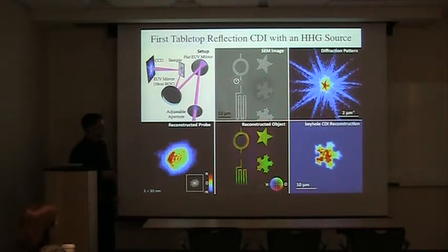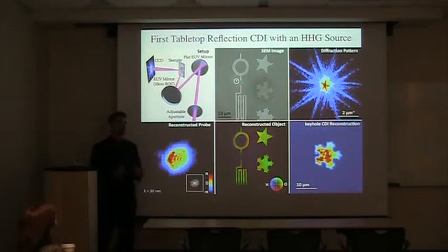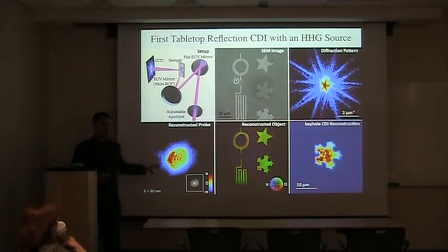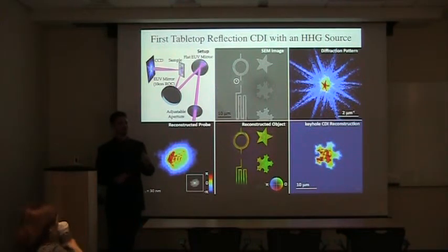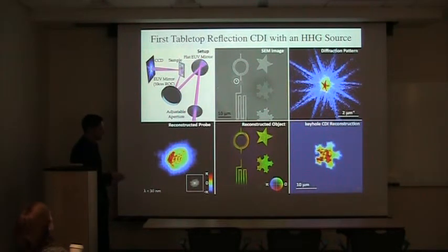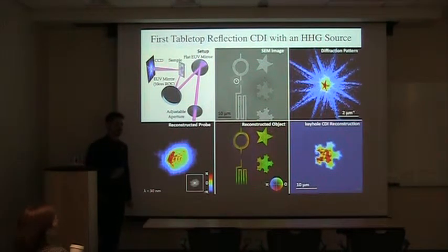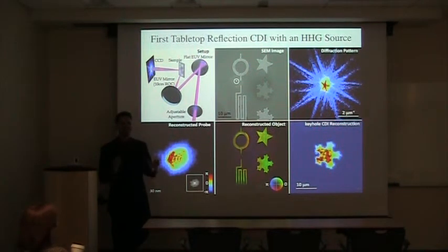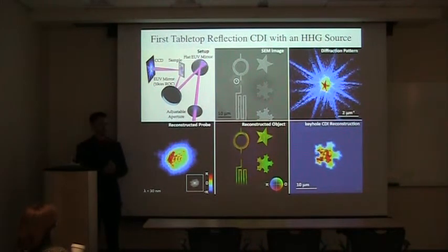Okay, like I said before, this new technique called ptychography is more or less a blind deconvolution algorithm. From it, you get your object and your beam, but it does require multiple diffraction patterns. Now, keyhole coherent diffractive imaging, if you know the beam, only requires one diffraction pattern, so it lends itself to dynamic studies. So you can get the beam from ptychography from this blind deconvolution algorithm using many diffraction patterns, and then plug that into the keyhole coherent diffractive imaging technique. So we have a lot of different techniques that we can use to do this imaging now.